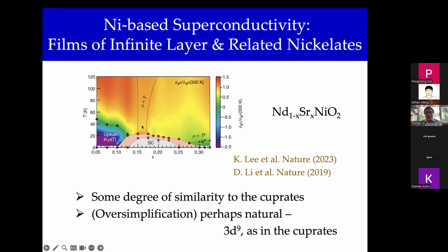It was not quite a coincidence to showcase a phase diagram like this, because part of the pursuit was to see whether the cuprates have counterparts in other families of materials. In a bit of an oversimplified picture, perhaps superconductivity in these nickelates is natural, in the sense that if you count the nominal valence, you end up with 3d9 valence, nine electrons in the 3d orbitals, for the parent compound, and that has some degree of similarity with the cuprates.